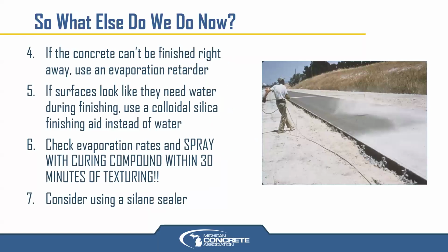And after that final texture has been put on, make sure we cure it like we see in the picture here. If it can't be finished right away, if there's a long distance in between placement and some finishing operations, or the finishing and then the texturing, or the texturing and the curing, spray it with an evaporation retarder. Try to get a film on there that will prevent the evaporation. And then the minute you start working it with the next tool, that evaporation retarder, that film is gone. And do not use it as a finishing aid.